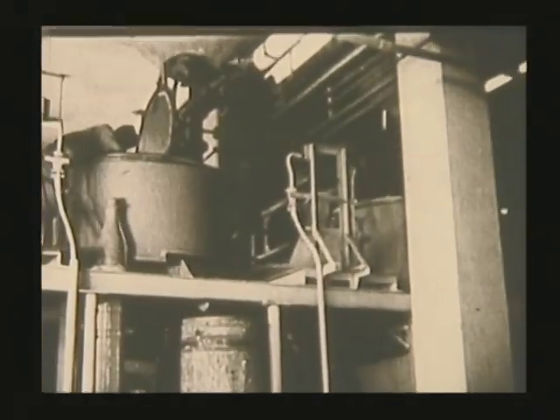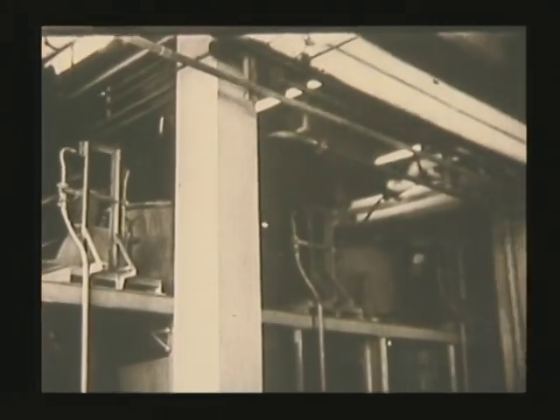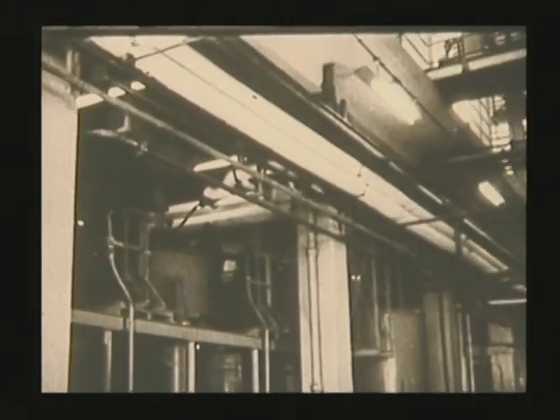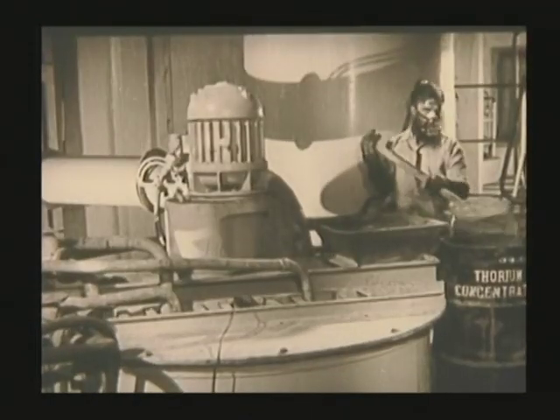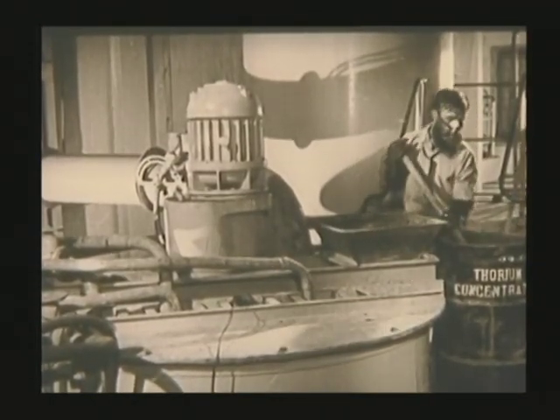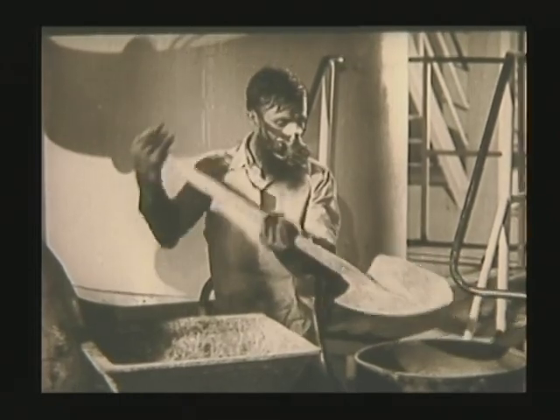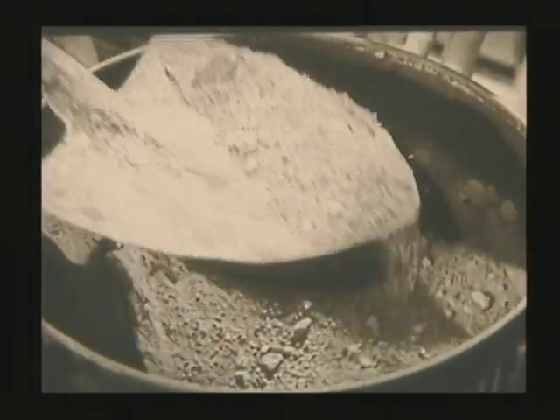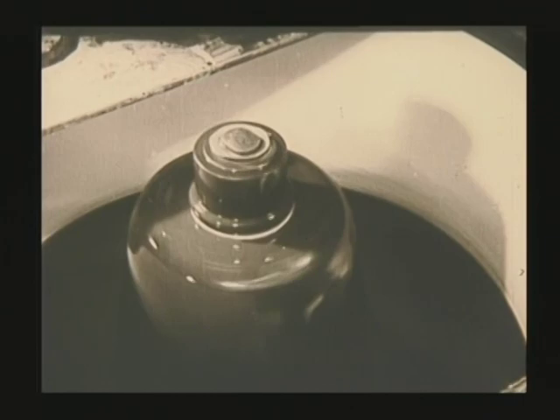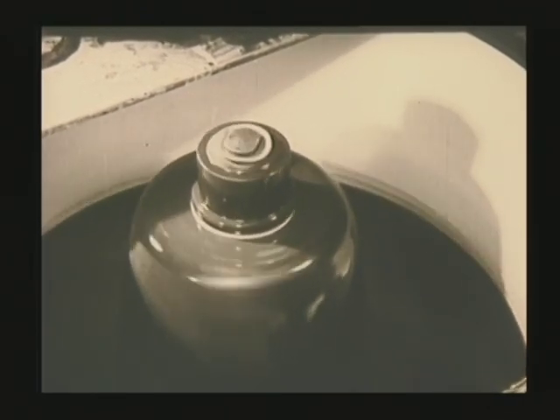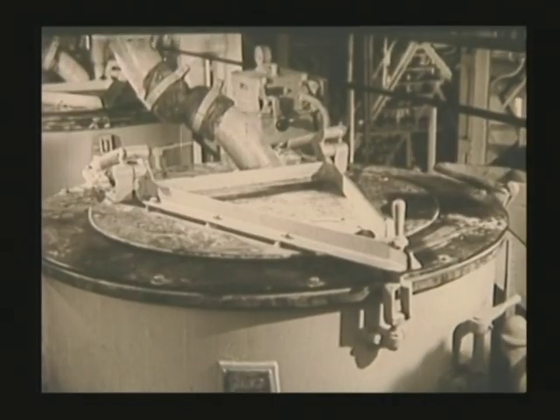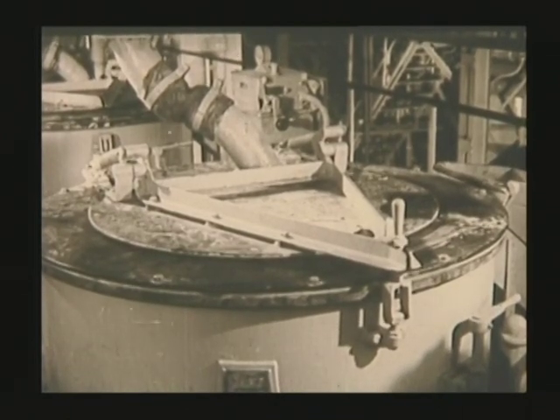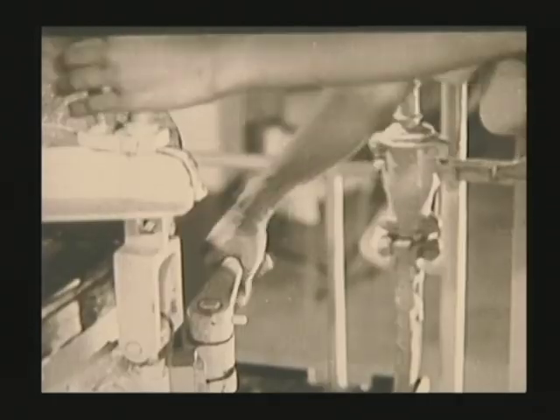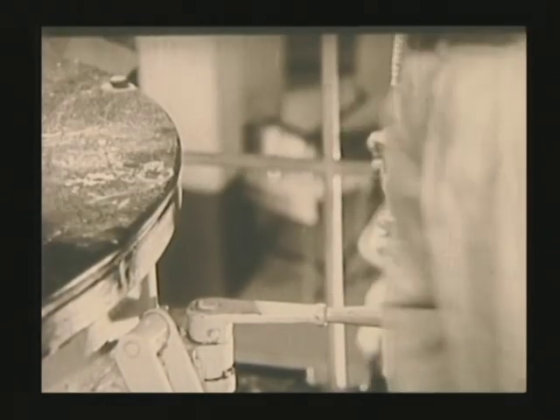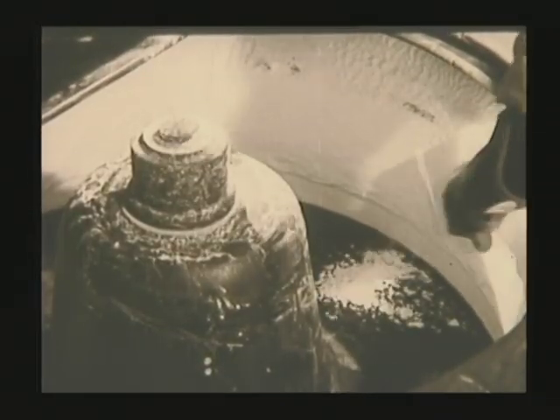The process in this plant forms the second stage in the treatment of monazite sand. Here, thorium-uranium concentrate is dissolved in hydrochloric acid and filtered to remove the insoluble impurities. Thorium is precipitated as a sulfate, leaving uranium in the mother liquor, which is separated by centrifuge. Thorium is further purified by reprecipitation as a sulfate.